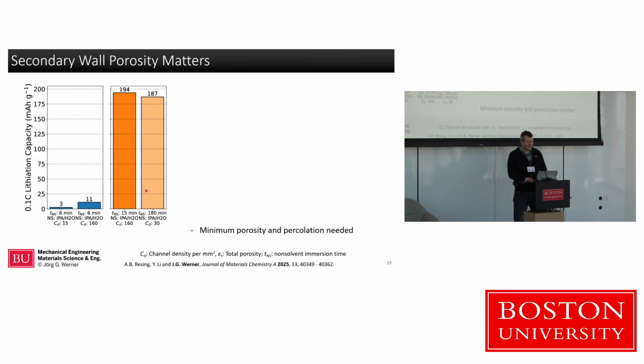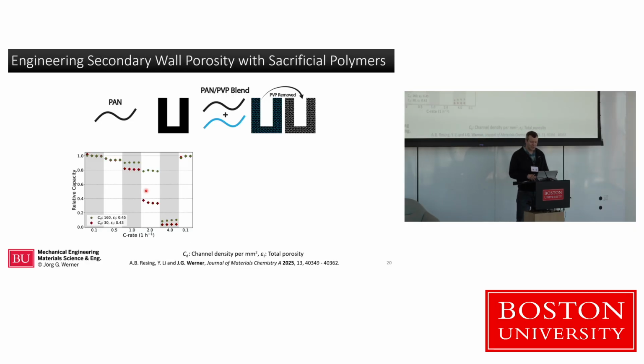Now, I'm running a bit out of time, so I'm going to skip over a couple things. I do want to note that so far I've pretty much only been talking about shuffling porosity between the walls and these channels. More channels and less porosity in the wall, or more porosity in the wall and less channels, to keep the overall porosity the same. We also realized, though, that the architecture of that porosity in the wall seems to really matter too, specifically the connectivity. We can have walls that have a bunch of pores, but if these pores are closed off, they're not really helping the ions to get through that porosity, right? Think of a closed pore sponge.